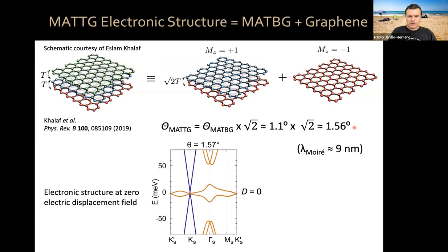Now, in this mirror symmetric configuration, this is the electronic structure for magic angle twisted trilayer graphene at 1.57 degrees. As you can see, we have a set of flat bands with remote bands, which looks very similar to magic angle twisted bilayer graphene, plus an additional massless Dirac dispersion, which comes from the monolayer graphene-like part. This is when we have zero displacement field. So all three layers, in addition to structurally being in a mirror symmetric configuration, electrically are also in a mirror symmetric configuration.